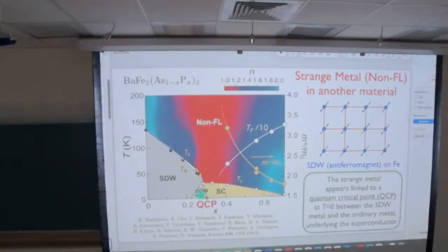And similarly, if we understood how the critical fluctuations pair the electrons, that will tell us why Tc is high. And in fact, it is a maximum right near the QCP. So this QCP seems like just the right thing to study the rest of the phase diagram. It's a thing you should try to understand. Okay, so that seems very reasonable for these pnictides. And a lot of progress has been made, although there's a bunch of subtleties trying to understand this red region from the QCP, even for this case, that I hope to get to fairly soon.